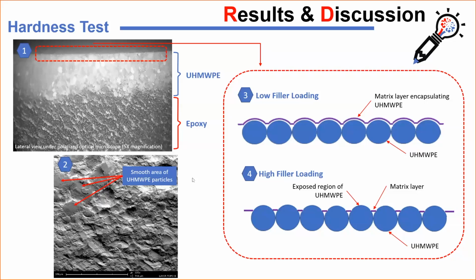For low filler loading, the deposition of ultra-high molecular weight PE particles on the epoxy surface seems to be encapsulated by a thin layer of epoxy, as illustrated in figure 3. The presence of this thin layer of epoxy contributes to the increase of hardness value up to 5 weight percent filler loading, due to the stiffness of the epoxy itself. However, despite the presence of this encapsulating layer, the low coefficient of friction of ultra-high molecular weight PE can still be disseminated to the composite surface, which is observed directly by the gradual reduction in specific wear rate in this graph.